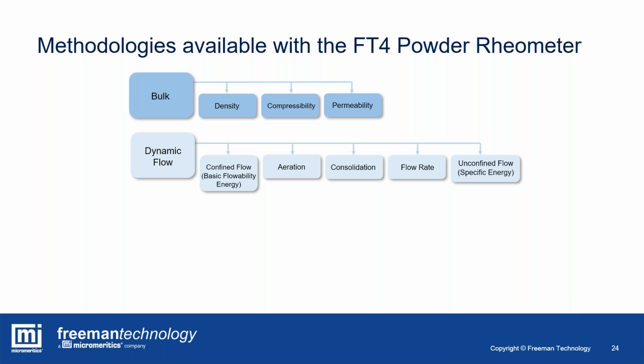And we also quantify something called the unconfined flow. This is a very important difference to the confined flow regime. This is about how material would flow without being imposed upon by an external stress. So this is really about whether something would flow under gravity, and it's dependent very much on the mechanical interlocking between the particles. Then we have shear methodologies, so the shear cell and the wall friction I just talked about.